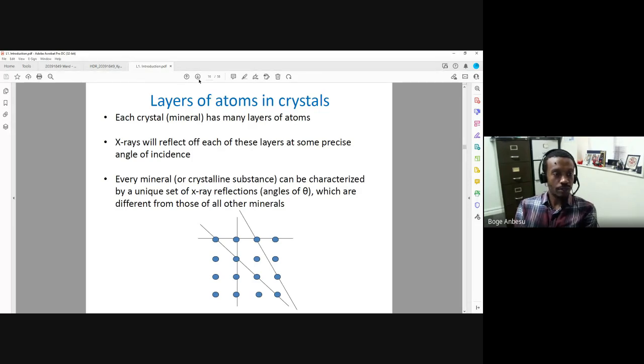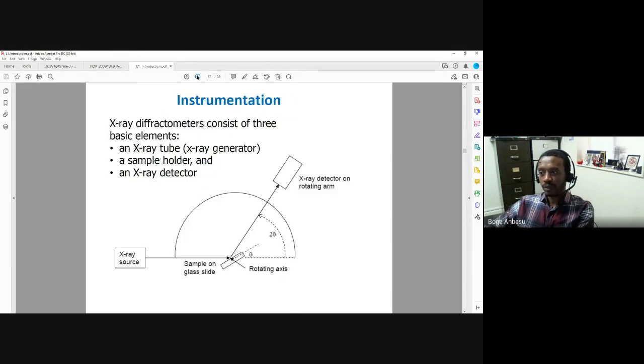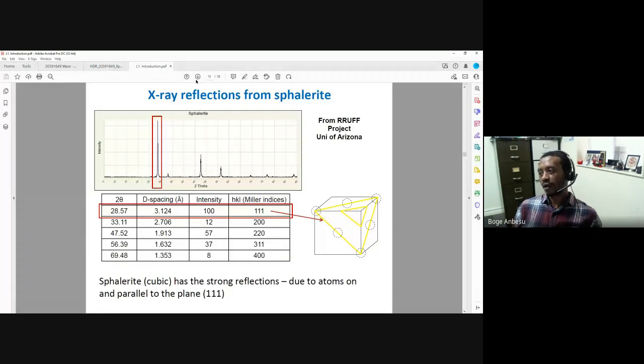So all we have to do is record the reflections of X-rays from the sample, which will be recorded in the detector, and you would have an X-ray spectra, which looks something like this. In this case, if I had sphalerite, I know sphalerite is made from an ordered arrangement of zinc and sulfur atoms, and there are a number of planes within the sphalerite crystal. From those planes, I will get different X-ray reflections, which can be recorded and presented as a spectra, which is what you see here. As you see, there will be a characteristic peak of sphalerite at 28.57, two theta, for example. And you look at another one, there's one at 33, one at 47.5, one at 56 and 69.